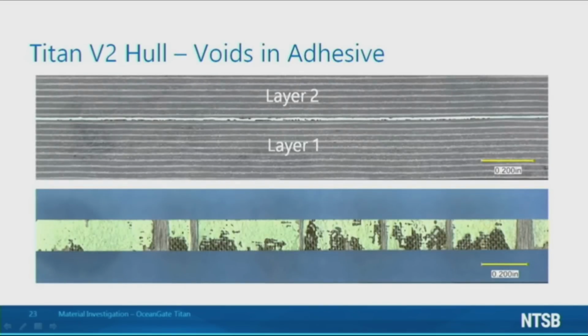The appearance and structure of the voids within the adhesive bond is illustrated by this laboratory fracture. A thin strip of hull material at the layer 1 and layer 2 adhesive joint was snapped open, and the resulting fracture surface is shown in the lower image.